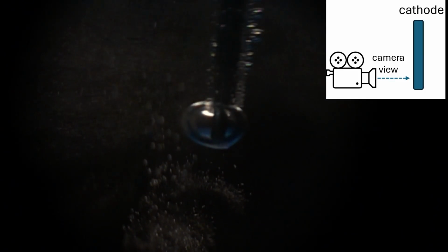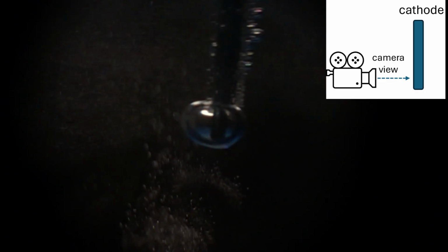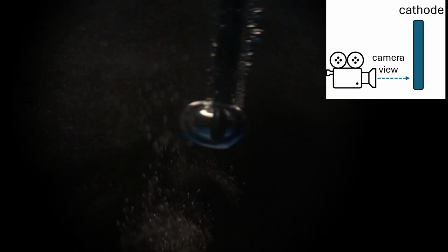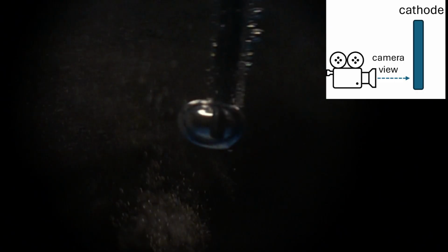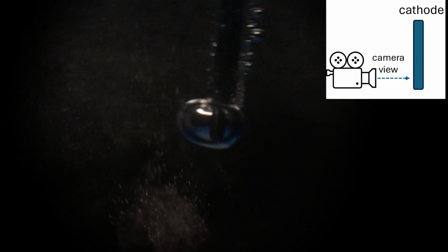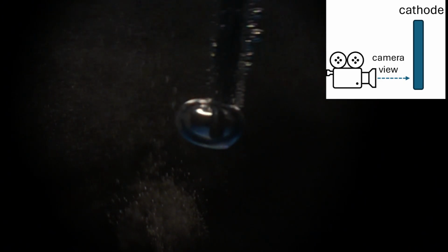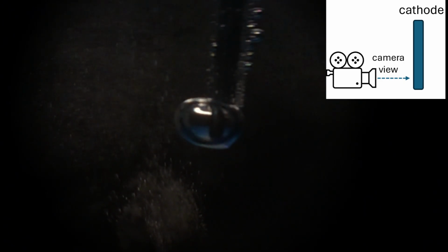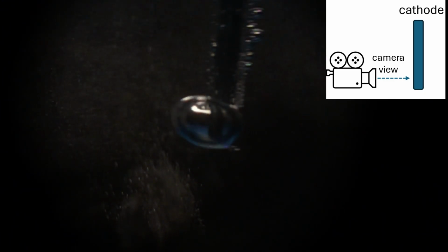The titanium electrode straight up and down, essentially vertically in the electrolyte, and you can see how as the bubble builds from the electrolysis products, as the gas evolves, it insulates the electrode, which in turn prevents the reaction from happening because the electrode is no longer in contact, except for in small parts with the water. And as soon as the bubble begins to break away and does break away, we see the reaction really take off again, and it restarts the process.